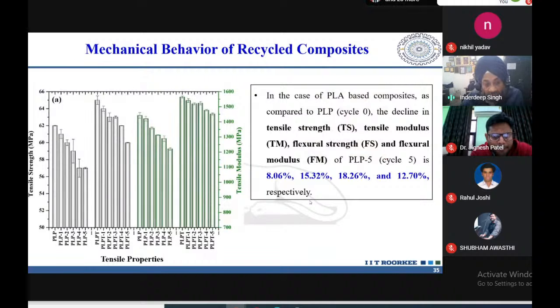So normally, if you see, we are talking about polylactic acid here. The tensile strength of neat polylactic acid is 54 megapascal, as supplied by the vendor who has supplied the polylactic acid pellets. And after adding fibers, short fibers also, normally we don't integrate short fibers for improving the strength of the matrix, but here, even with short fibers, the strength is improving. For example, you can see here the 54 is marked in blue color.